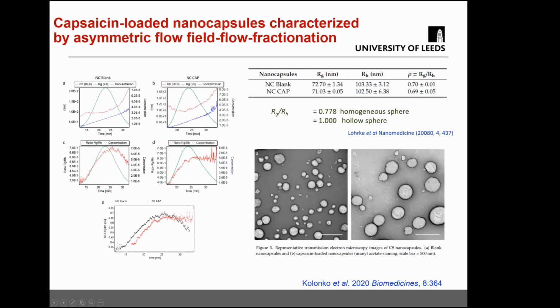Now, we've been using a platform here in the lab in Leeds to characterize not only biopolymers, but also particles. It's called asymmetric field flow fractionation. What I'm showing here on the left panels are size distributions obtained by fractionation using this technology. The power of this is that we can characterize not only the size, we can also see several populations. What I'm showing here are capsaicin-loaded nanocapsules.